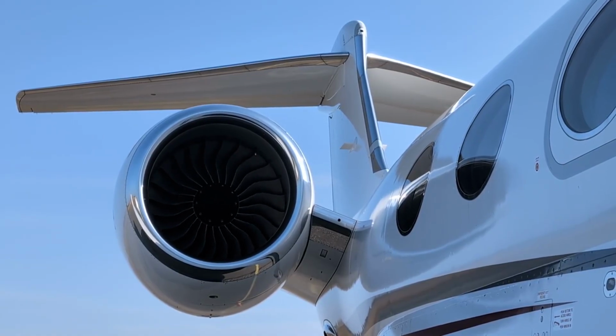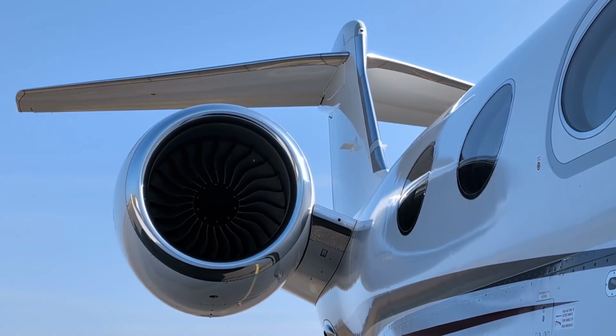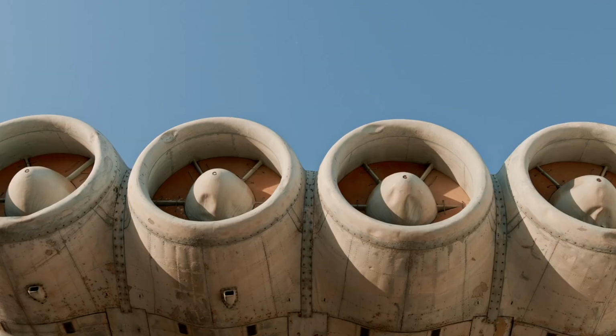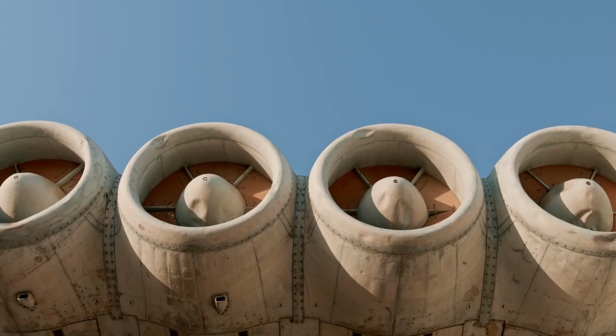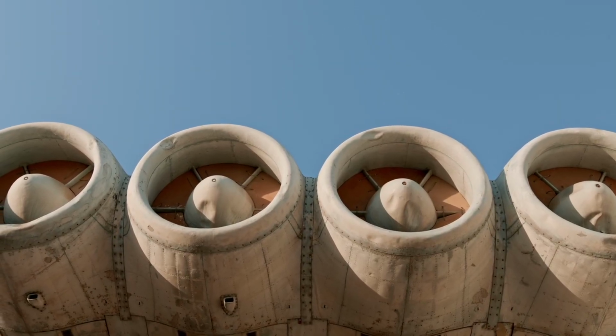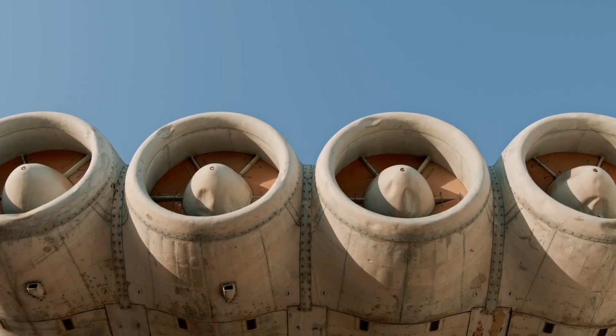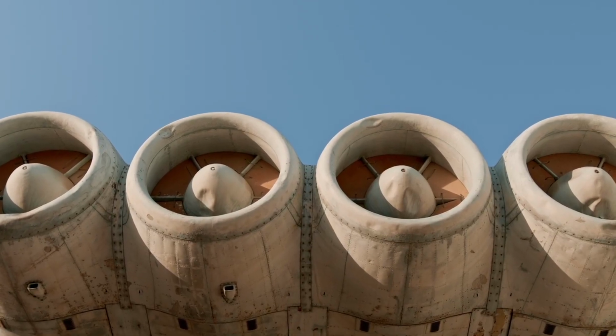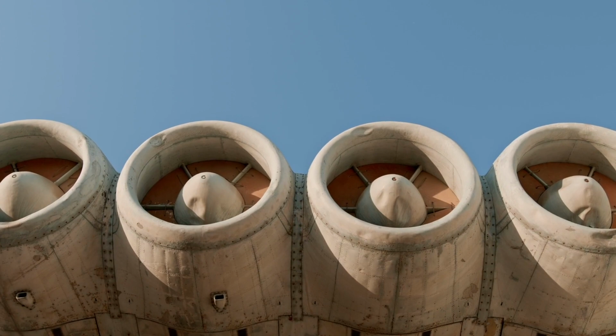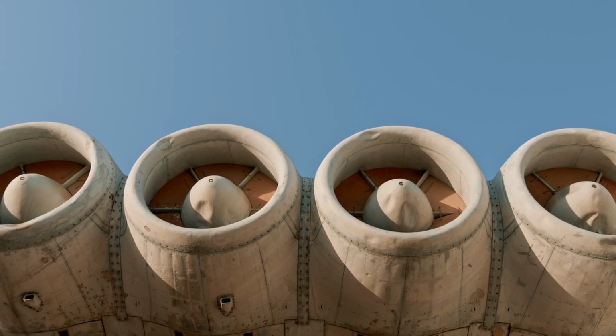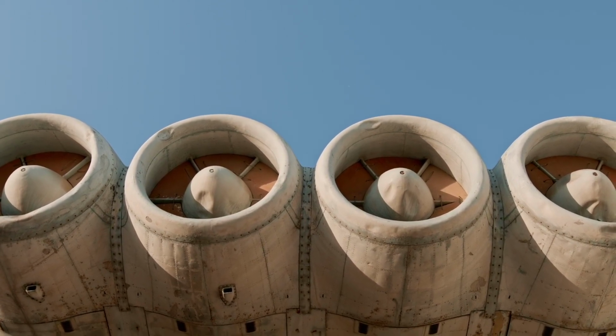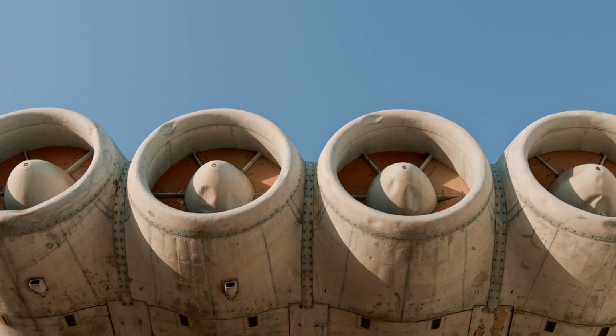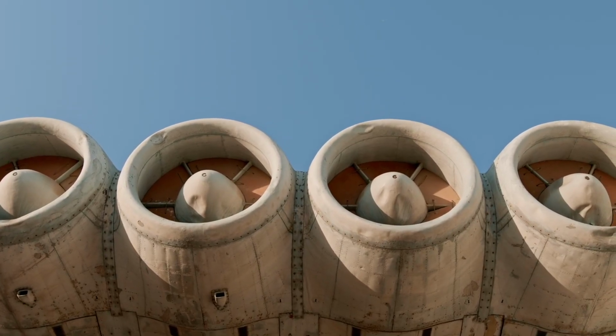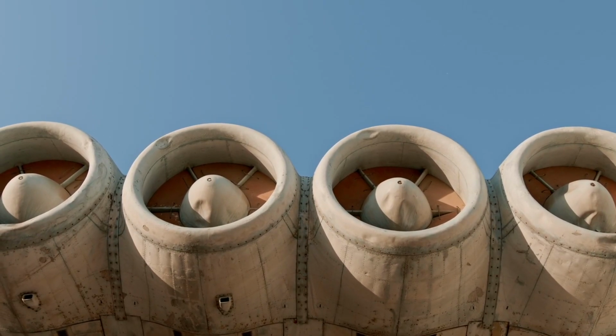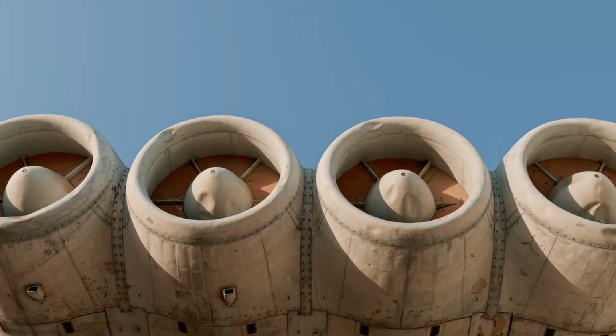That defect reached the bore of the disc, and the crack grew from there. The disc bore is the inner surface of the central hole, the one that fits over the engine shaft. It's one of the highest stressed regions of the whole part because that's where hoop stress concentrates as the disc spins. A crack originating there is about as bad a location as you can pick, and the bore is the piece of geometry this entire story turns on.